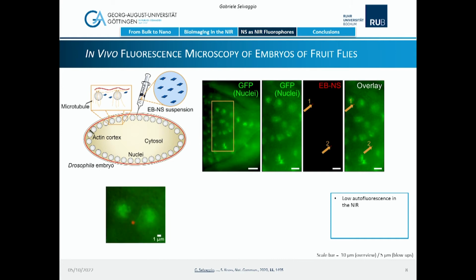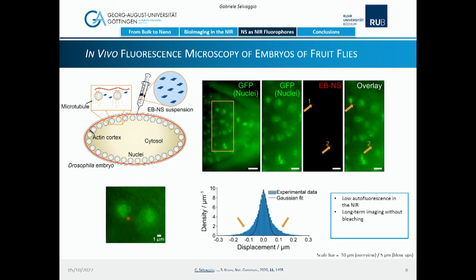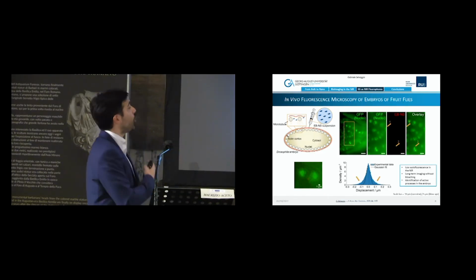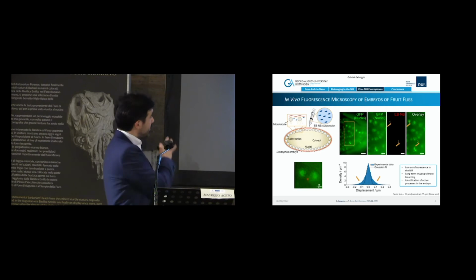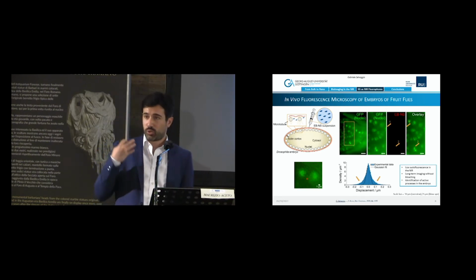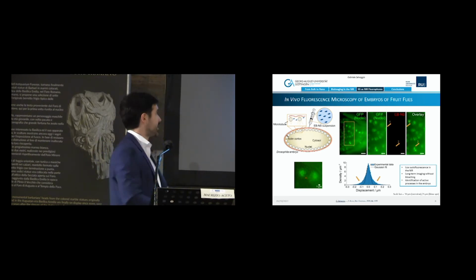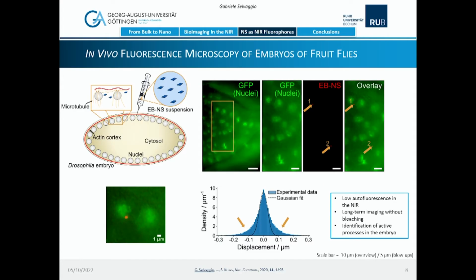And thanks to the properties that we mentioned earlier of Egyptian blue nanosheets, that is, that these nanosheets don't bleach, we were able to image them on a long term and perform particle tracking while these embryos were growing. And in this way, with particle tracking tools, it was possible to identify active processes ongoing in the embryo. And this is just a proof of principle application that shows that you can use Egyptian blue nanosheets as near-infrared fluorophores for in vivo fluorescence microscopy.